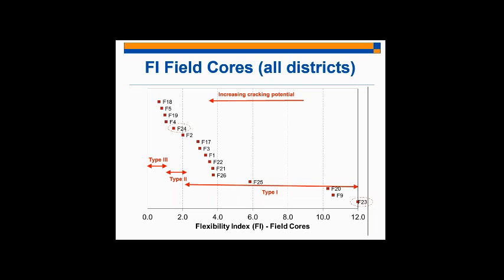And I want to discuss two special field core mixtures that we tested. So the F24 and the F23. We actually have field surveying data or performance evaluation data from the field for all these mixtures. And the F24 mixture displayed very poor field performance, while the F23 mixture displayed very, very good, excellent field performance. And so we can begin to see our flexibility index being validated by field performance.